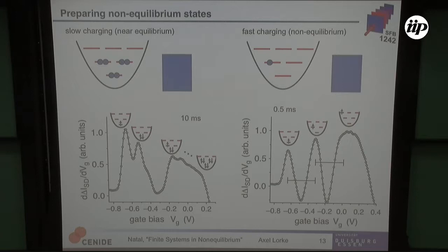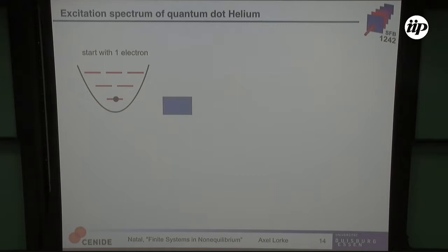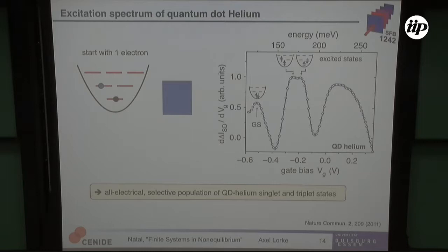So now we can use the combination of the two to look at electron-electron interaction in these few particle systems. And we do that by setting our starting Fermi energy high enough that we fill a single electron in each of the dots, and then bring the Fermi energy up quick enough that the excited states will be filled. And then we see the two electron ground state and the two electron excited states. And here you see a splitting, which comes from the fact that one of the two is tunneling into a triplet state and the other is tunneling into a singlet state. And the difference between these two states is exactly the exchange interaction.